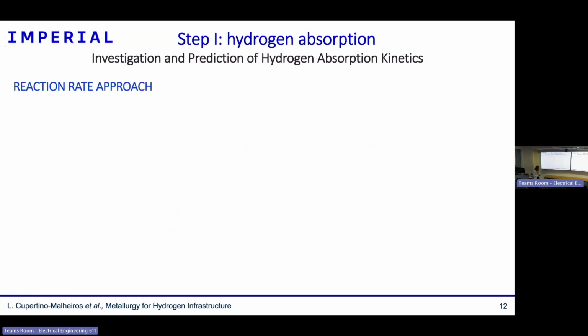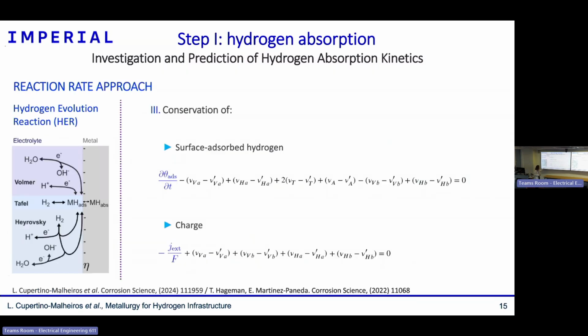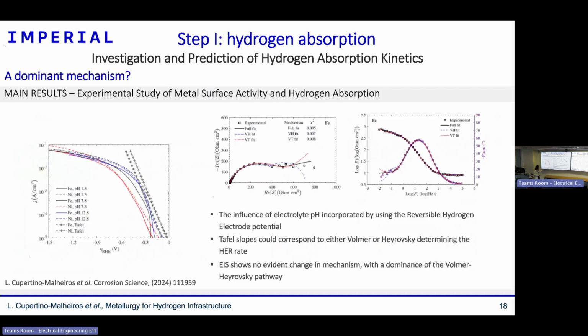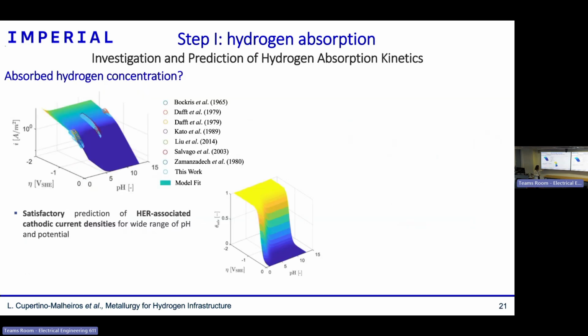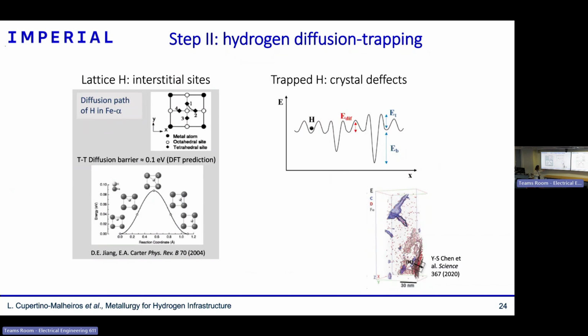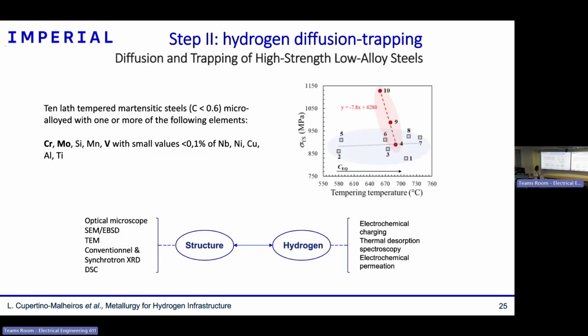Okay, I didn't mention much this aspect, so I think it's about diffusion and trapping, if that's the case, about carbides. Those are carbides that I didn't really observe for these steels. Even though it has chromium, I think M23C6 is rich in chromium. In those steels the maximum was 1% of chromium. We didn't observe that, so chromium was mostly inside of cementite.